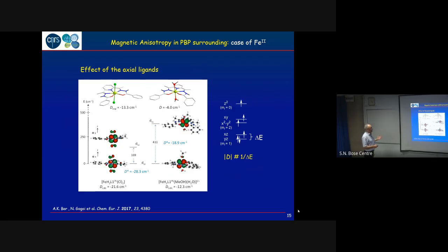However, what happens also is the energy of the anisotropy will depend actually on the energy difference between the two orbitals involved in the first excited state. So here I take an example where you have two very closely related complexes, but only the ligand in the apical position is changing. Here it's chloride, and here we have water molecules. And you see that this makes a difference in the splitting of these two orbitals. Here we are, let's say, a difference of 170, and here it's roughly 400 inverse centimeter. And of course, the contribution to D is inversely proportional to that. You can see this is much larger than the one we have. So these are things you have to control or take into account if you want to use magnetic analysis.